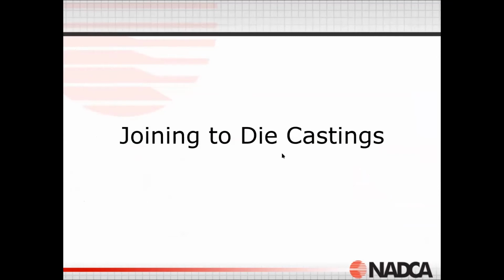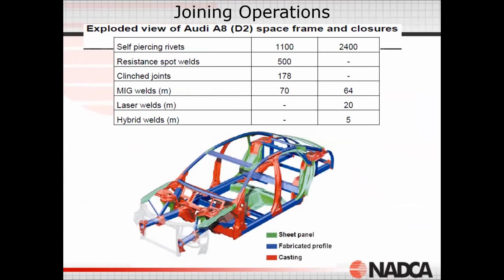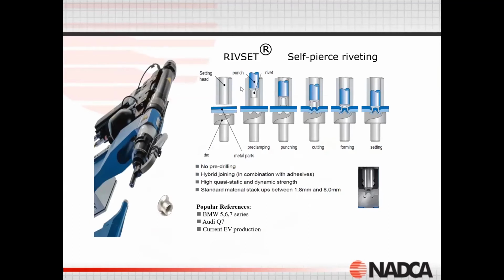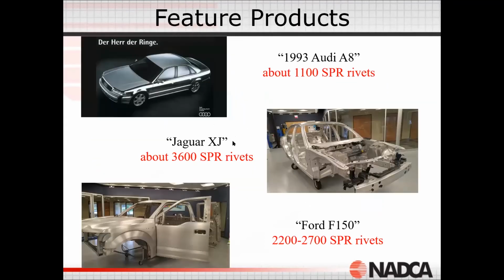When we're looking at these castings, we have to use joining operations to bring them together with other components. So we use riveting, spot welds, clinching, MIG welding, laser weld, all different processes for bringing together these components. One of the projects that NADCA is working on is riveting, and so we're working with Böllhoff, a company, to help us further develop the riveting of aluminum castings. So riveting has been there for many years, and we're looking at improving that. So the riveting of these type of structural alloys is more uniform, more reliable. So we can see a component like the Ford 150 has between 2,200 and 2,700 rivets that join all the different aluminum components together.